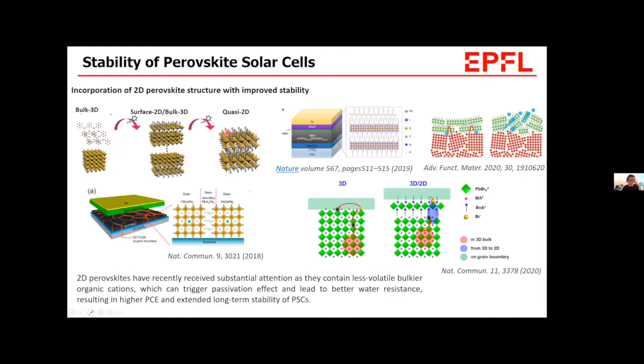So there have been various approaches to improve the stability of perovskites, and use of low-dimensional perovskites, such as quasi-2D or 2D perovskite, can effectively suppress ion migration, so that it improves stability of perovskite and devices. So this low-dimensional perovskite can be formed. I mentioned the tolerance factor. When the size of the A-site cation is getting bigger at a point, the perovskite cannot maintain its three-dimensional structure, but it forms into this kind of low-dimensional structure.